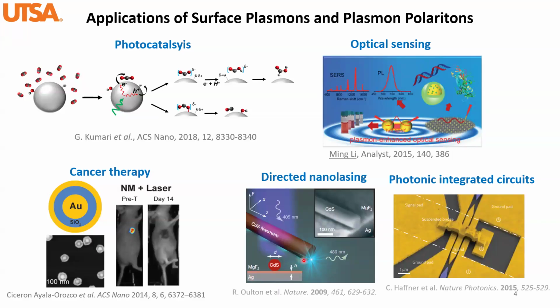In these two cases, it requires the plasmonic surface, and in the nanolasing case, it's actually a Fabry-Perot interferometer, and this semiconducting nanowire is being excited and emits light. And then there is a spacer between the semiconductor and this plasmonic surface. This way, it traps the light within this tiny little spacer, so it is more confined and well directed. And for the photonic integrated circuits, in the case of plasmonic applications, it's more about plasmonic waveguides. And this has really great promising applications in optical quantum computing, data transfer and storage, and communication as well.